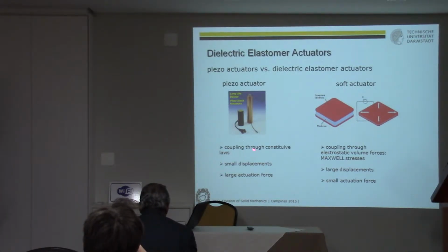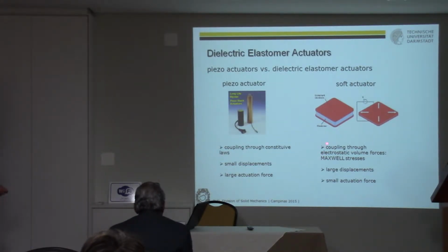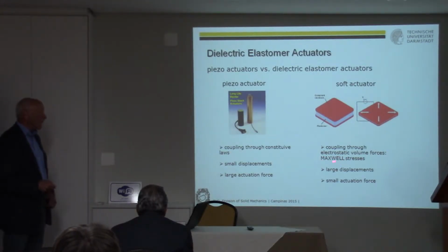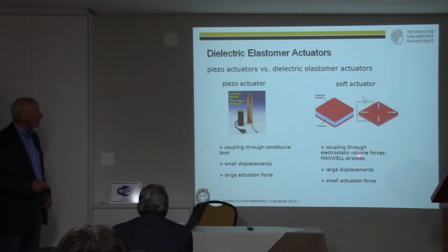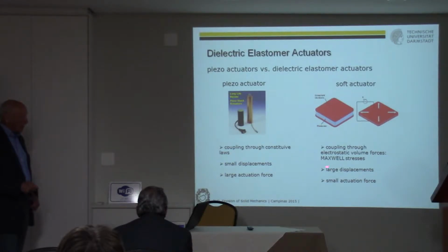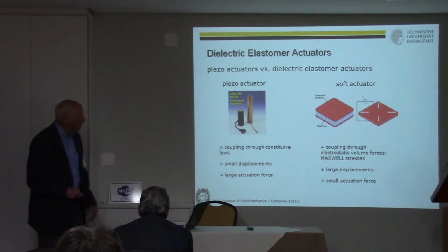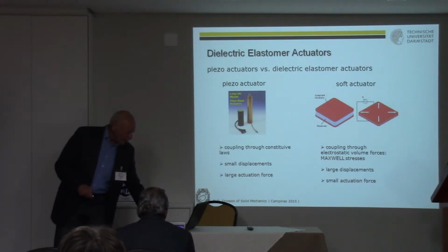Okay, a piezoelectric actuator, here the coupling comes through the constitutive laws, and you have only small displacement. This means it's very simple. You can apply small strain theory, and you can get large actuation forces. And in a soft elastomer actuator, the coupling between the mechanical and the electrical fields comes only through the Maxwell stresses, and electrostatic volume forces. You can get large displacements and only small actuation forces. But for certain problems, this is exactly what you want.